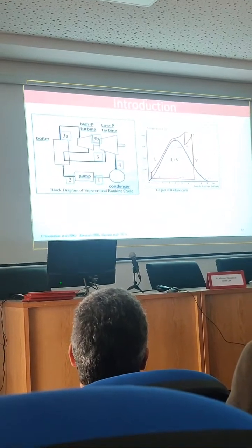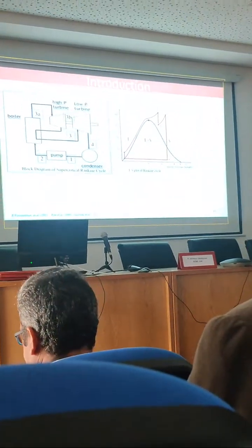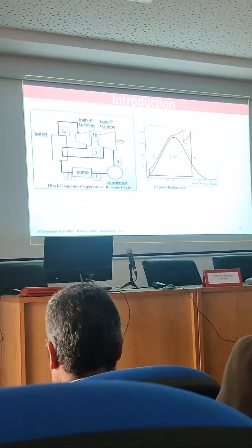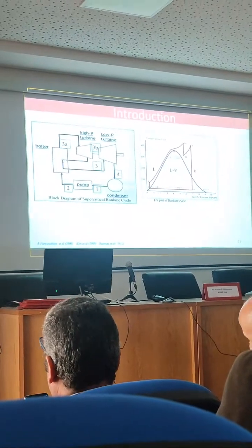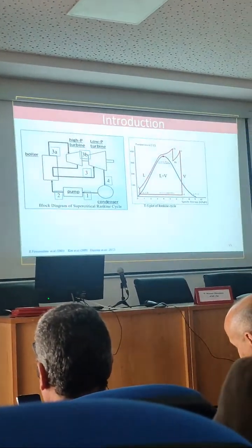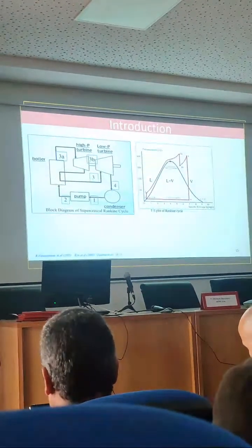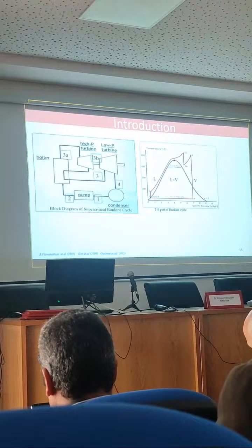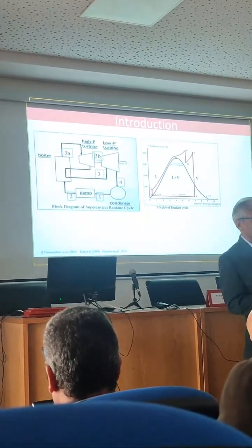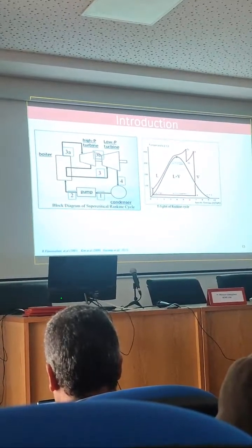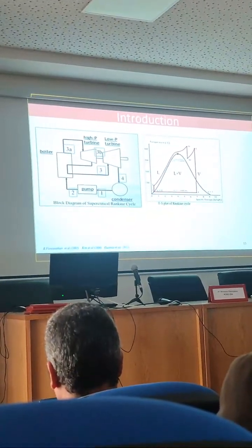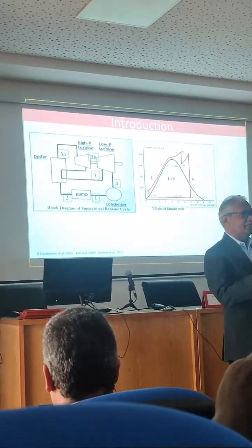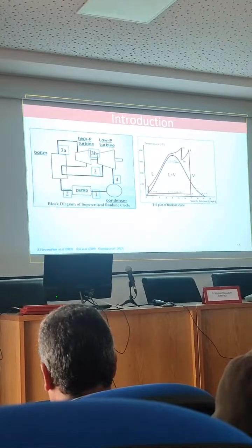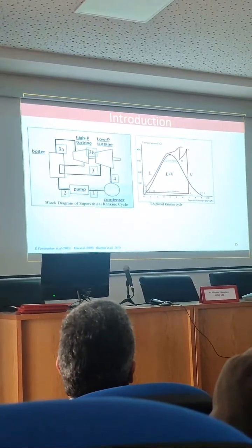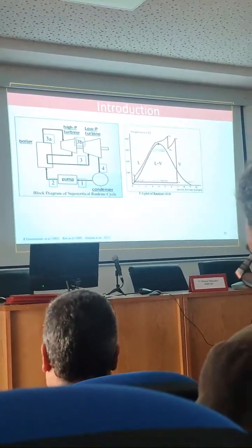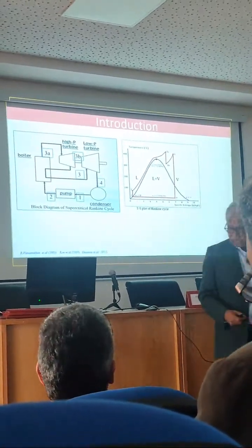But if I can pressurize it, heat it to 700 degrees Celsius, don't allow the steam to form. Keep the water in the same liquid state, at 700 degrees Celsius, don't allow the vapor to form. Then the heat transfer becomes extremely large. When you form a gas bubble, the thermal conductivity becomes a problem. Apply the high pressure, don't allow the water to evaporate, then the heat transfer between the fuel on this side and the steam on this side is very efficient. The boiler is a very efficient way of transferring the temperatures, right?